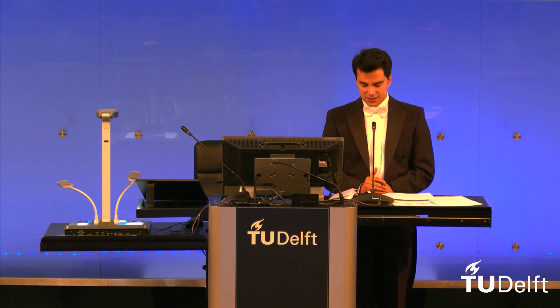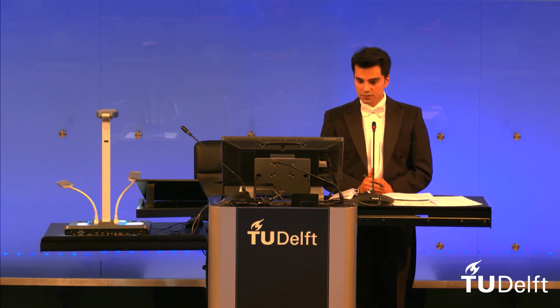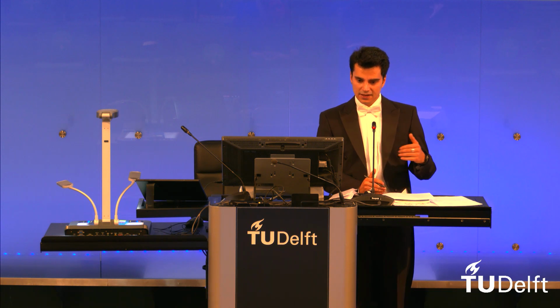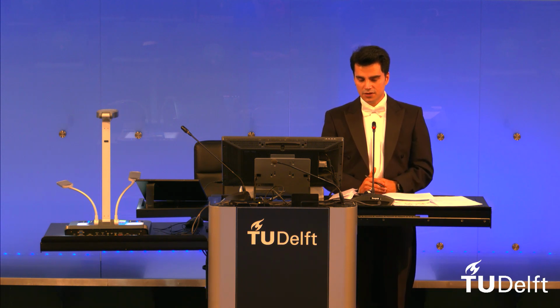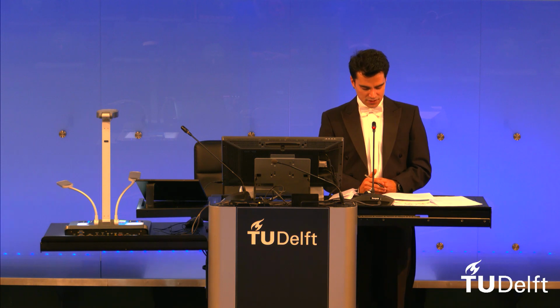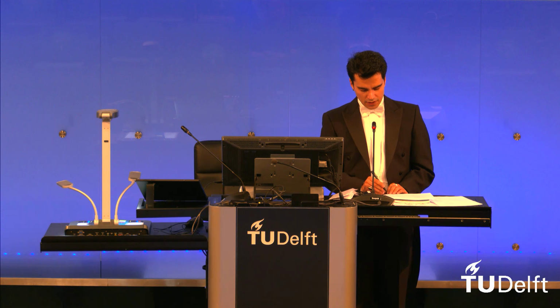Hooggeleerde opponent, about the exposure time, it takes around a couple of hours in order to perform a CT scan on each sample. And so I would say half a day would be enough to complete the CT scan, but part of this time is also considered for gathering and storing the results on the CT computer next to the device. So I'm not sure if the total couple of hours, half a day, would be necessary in order to do the CT scan. Why half a day? Why not 1 hour? Why not 5 days?